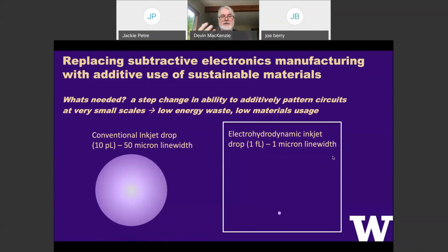So one of our specialties in our lab is printed electronics broadly. And of course, I've spent plenty of time working on conventional flexographic printing or gravure printing, conventional inkjet, where a drop is say 10 picoliters, and maybe you can get 1 picoliter, but that's somewhere between 50 and 10 microns of effective printed line width because the drop spreads. And by contrast, we're now working with electrohydrodynamic inkjet, where we use extremely high electric fields to break through the surface energy barrier for very small drops.